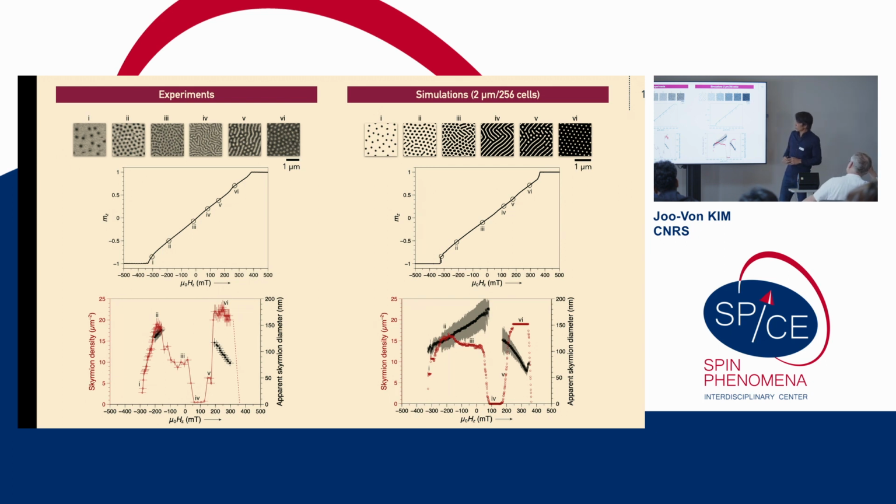And we also find pretty good agreement for the skyrmion density. So these are the curves shown on the bottom here, the red indicating how this density varies as a function of this perpendicular applied field. And quite notably, we reproduce this plateau here in the density, which corresponds to this skyrmion lattice state. So this is also something that we see in experiment.